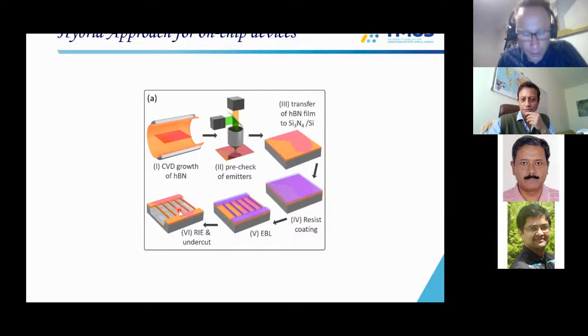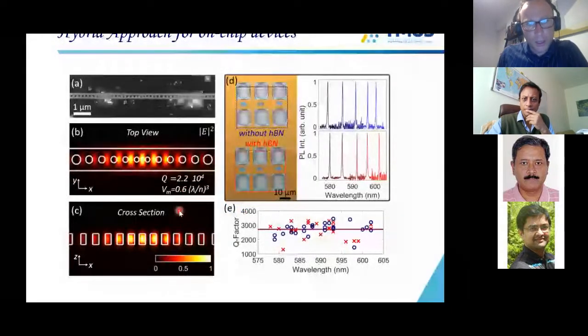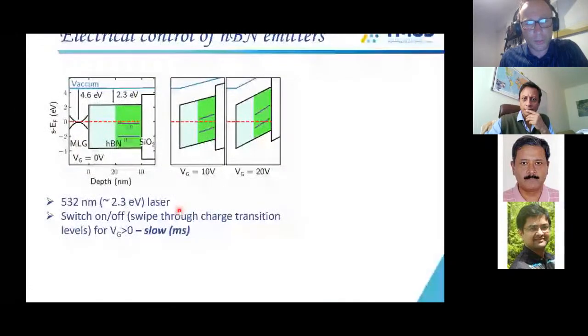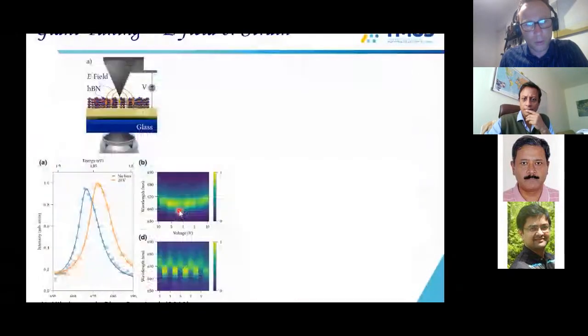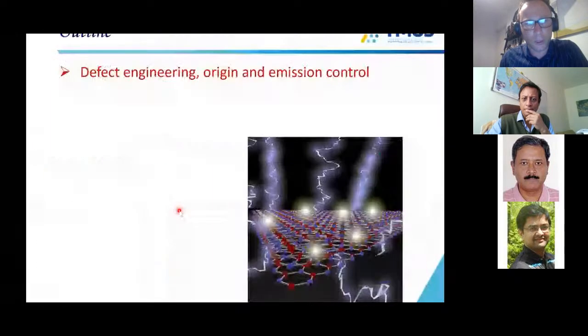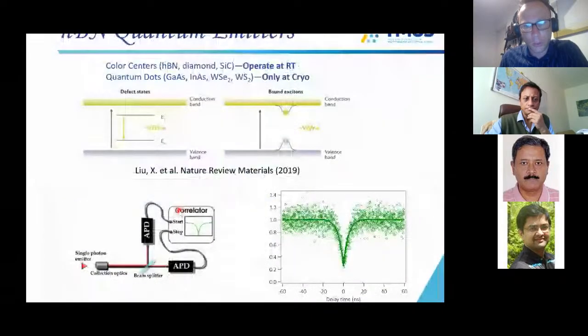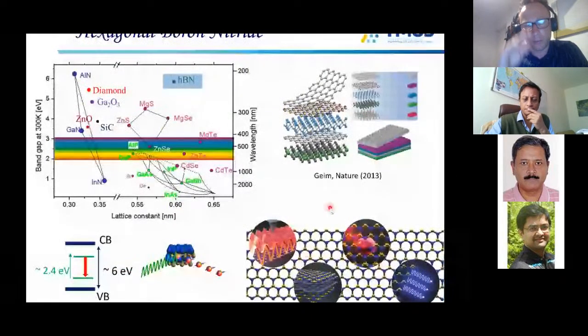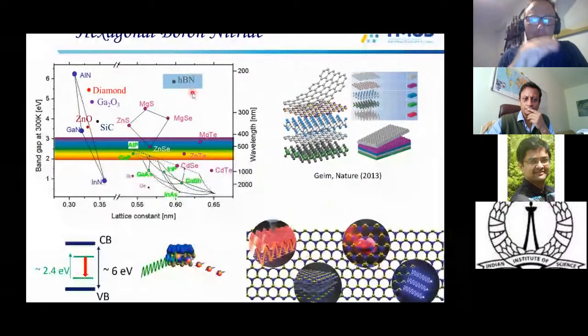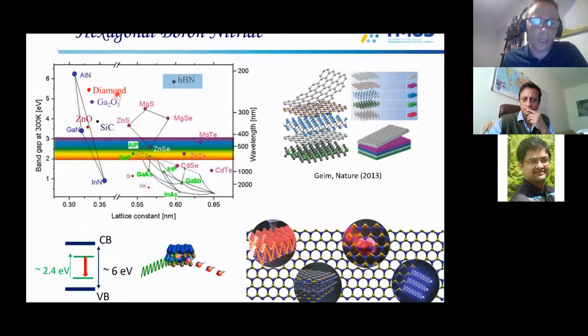Yes. The unique thing about hBN is that you can actually use it as a 2D system. Let me go back to the introduction. If you take any other form of BN, you can't really exfoliate it into 2D. The hexagonal structure of boron nitride is the only one that can really be exfoliated into monolayers or atomically thin systems. This is important because it provides ease of scalability. For example, if you want to make a cavity out of diamond, you need to somehow make a diamond membrane or make the diamond suspended. In hBN, you can simply suspend it over a silicon ridge and get it there. So it's really about scaling up your system. That's the advantage.